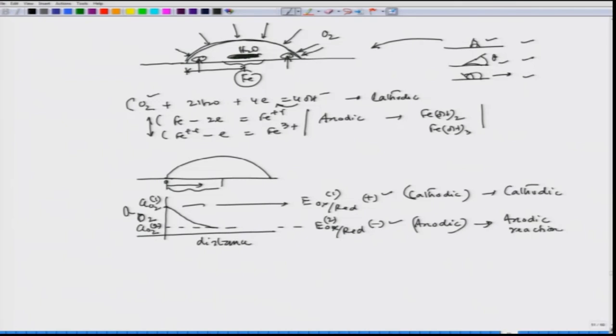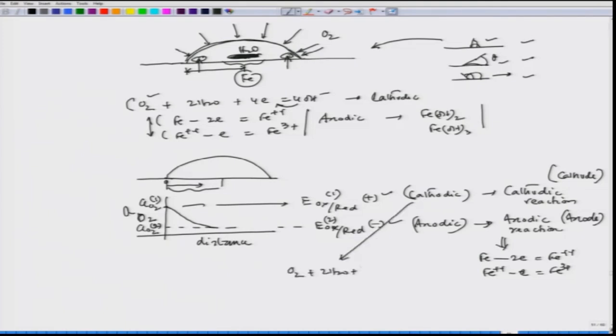So, in the cathodic zone, we have cathodic reactions. So, this becomes the cathodic reaction zone, this becomes cathode, this becomes anode, and here the anodic reactions would be Fe minus 2e equals Fe2+, Fe2+ minus e equals Fe3+, whereas here we will have O2 plus 2H2O plus 4e equals 4OH minus. So, in this zone we have cathodic reaction and in this zone we have anodic reactions. The cathodic reaction is this one and the anodic reactions are these two.